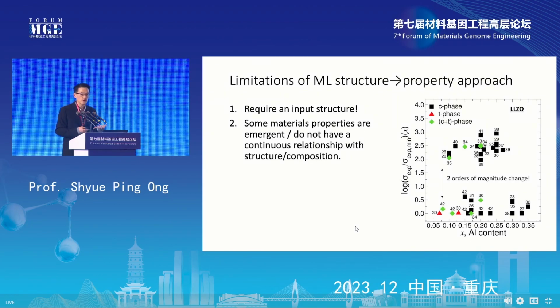So one of the big areas that I work on is lithium-ion batteries, right? And we work on solid electrolytes for all solid-state lithium-ion batteries. And one of the most famous solid electrolytes is called LLZO, or lithium lanthanum zirconium oxygen garnet, okay? And this is actually an experimental result which shows you that just by very, very small changes in the composition of LLZO, if you just dope it with a little bit of aluminum, you actually can get very, very large changes in the ionic conductivity of LLZO, right?